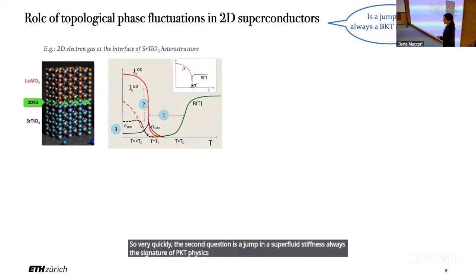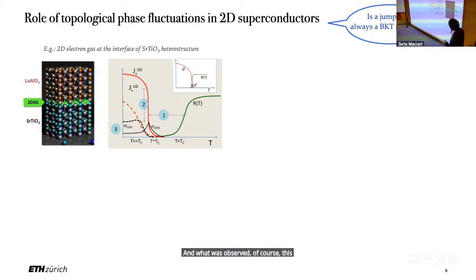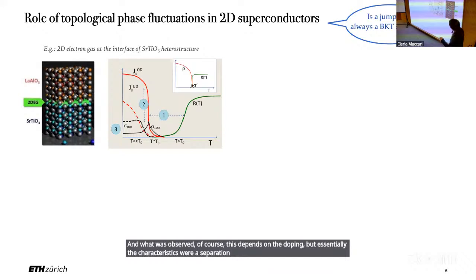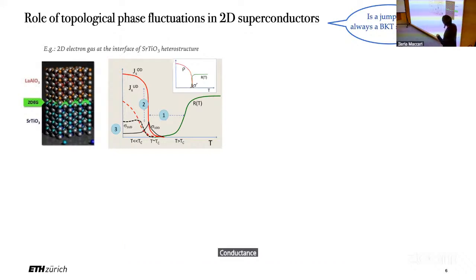So very quickly, the second question: is a jump in the superfluid stiffness always the signature of BKT physics? This is another research line we pursued in Rome, where we studied the anomalies observed in the 2D electron gas at the interface between two oxides. And what was observed, of course this depends on the doping, but essentially the characteristics were a separation with respect to the expected trend between the vanishing of the resistivity and the onset of a superfluid response, and also an anomalous conductance here at zero temperature.